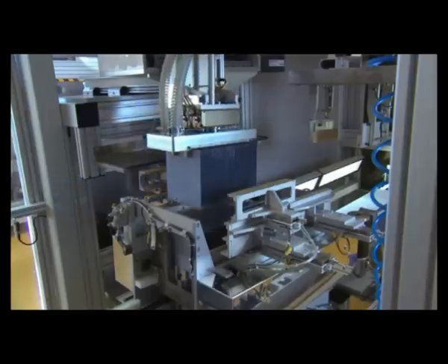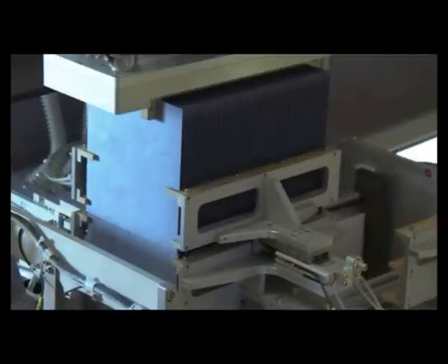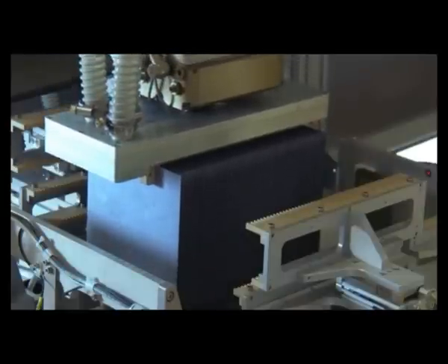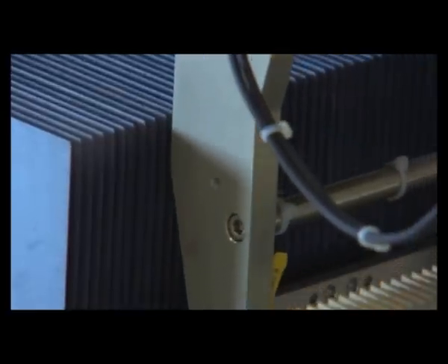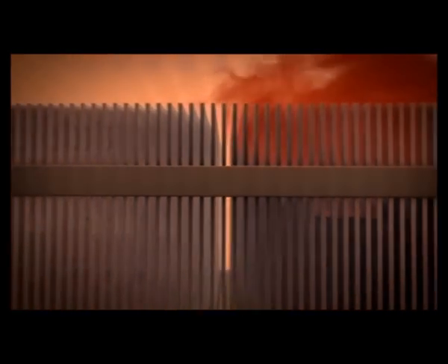Before this point is reached, however, our wafers must pass through a number of processing steps, the most important of which is probably a phosphorus diffusion step. In pairs of cells, placed back to back with one another, the wafers enter a tube furnace, where they are heated to over 800 degrees Celsius and diffused with phosphorus gas. This gas condenses on the open surfaces of the wafers.